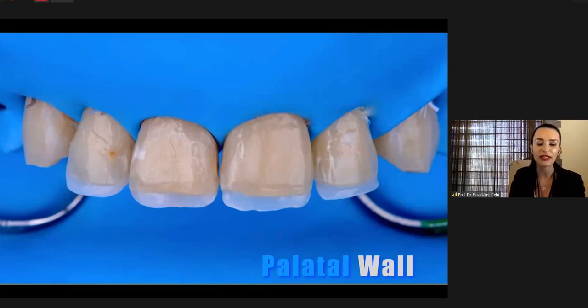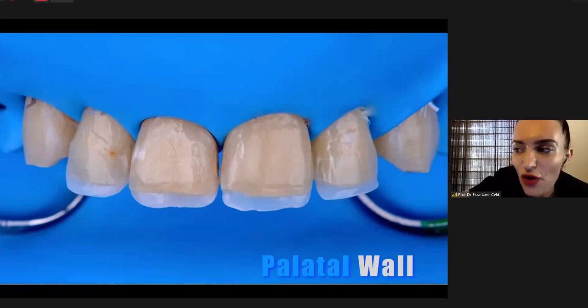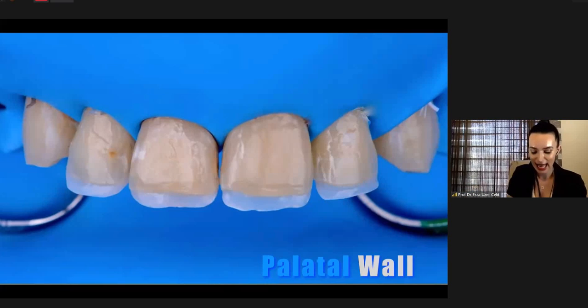The first step is creating a palatal wall. Apply the composite first under the silicone index and adapt it to the palatal wall. The thickness of the palatal wall should be between 0.3 to 0.7 millimeter, and you can use enamel or incisal shades to create this palatal wall.